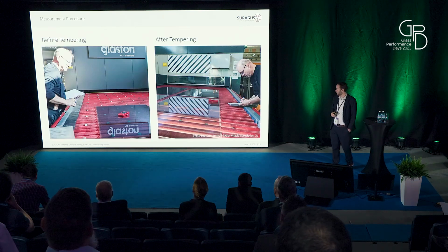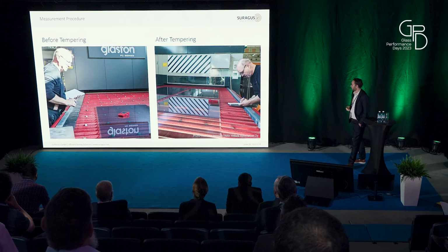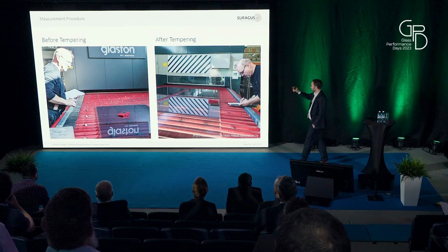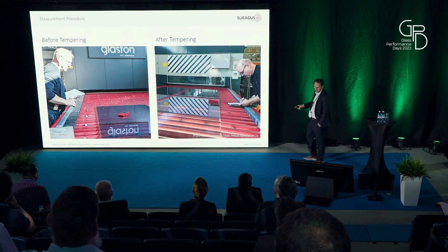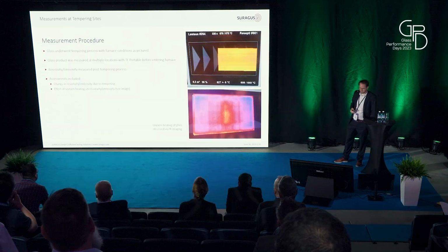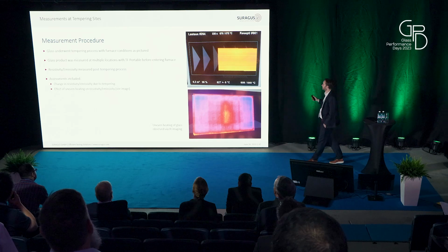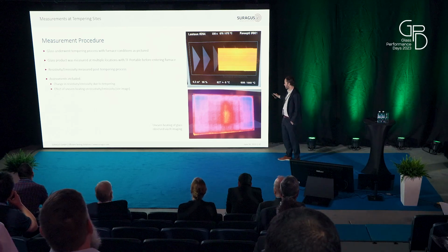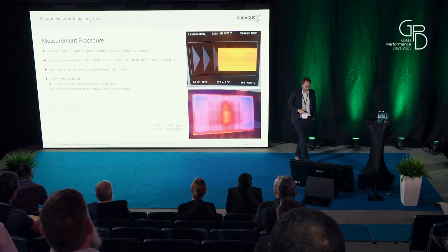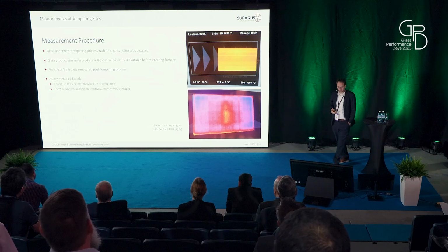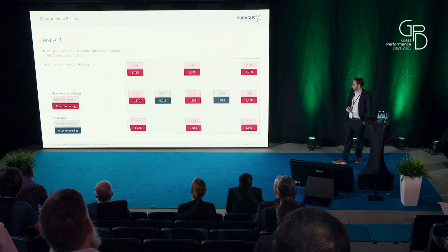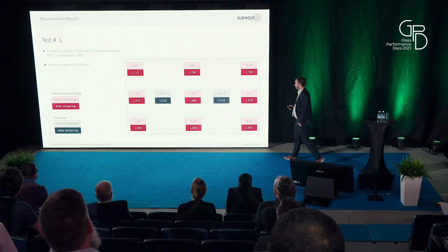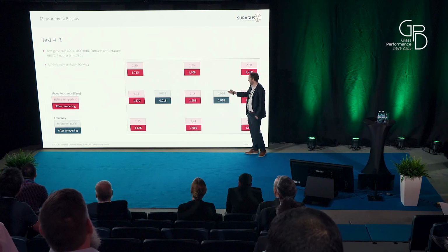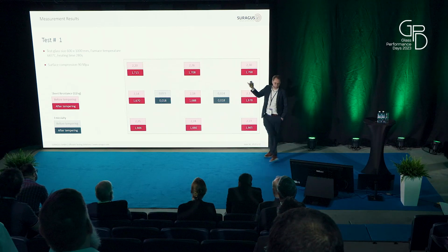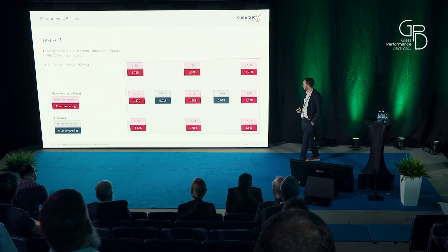We were measuring before and after tempering. So basically, after loading, measuring on different positions on the glass, and then after the tempering, getting the data. That was the process, and we were also looking at the recipes and the temperature which was applied. We also looked at the infrared images, and we tried to collect as much data as possible. The results look like this. For instance, here we have the emissivity before the tempering, and here we have the emissivity after the tempering. The other values are sheet resistance. Since sheet resistance and emissivity correlate, I show them both.